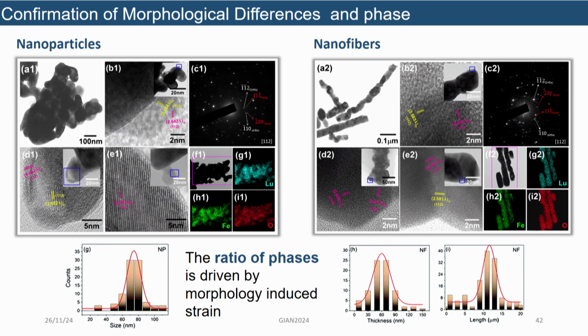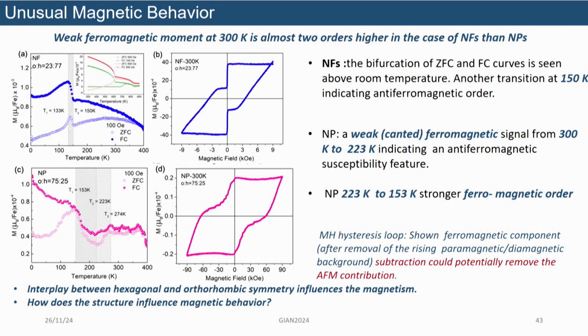So, we did TEM. We realized that the sizes and everything are in the range which can be called nano, and then we also found out with the high resolution TEM and diffraction pattern that both the phases exist in the material. So, it was very well confirmed. Then we observed the magnetic behavior, and you should see it is the same material, lutetium, iron, oxygen, but you have different magnetic behavior for the nanoparticles and for the nanofibers.